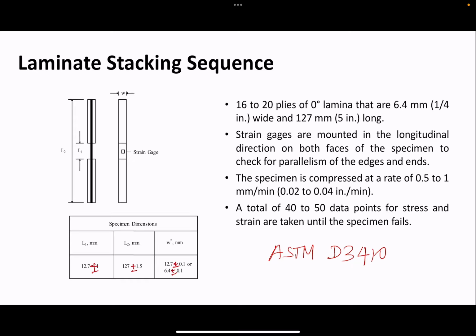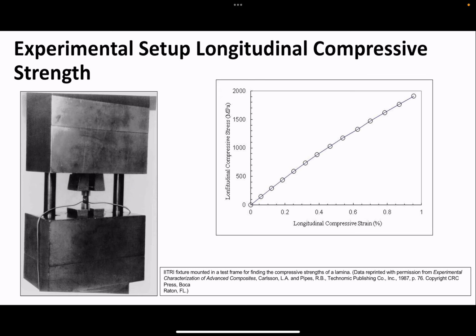So strain gauges as usual are mounted in the longitudinal direction. The specimen is compressed at a given rate, and 40 to 50 data points are taken for stress and strain until the specimen fails. And then in typical fashion, you draw the stress versus strain diagram. Here you can actually see the compressive specimen setup. So again, it's the same process.